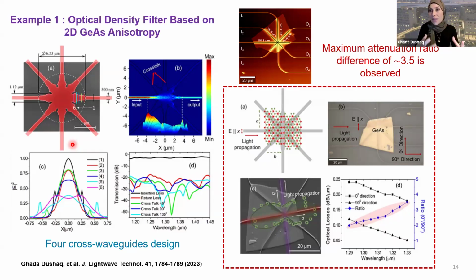So it acts like an optical density filter that can attenuate the light, depending on how much. So we have a maximum value, we have a minimum value, and values in between depend on the angle that we designed our four-waveguide crossing. But the idea was to understand the in-plane optical anisotropy of this material.